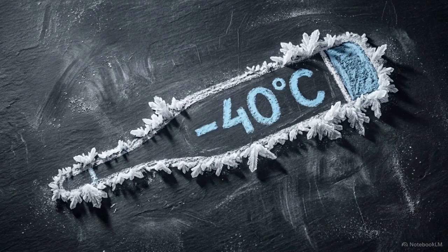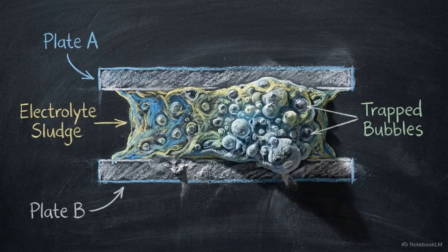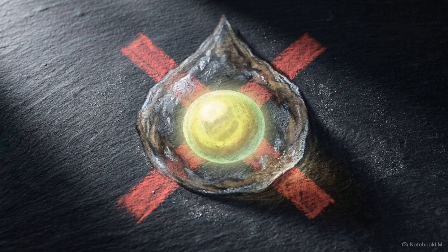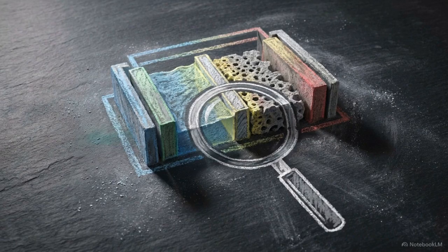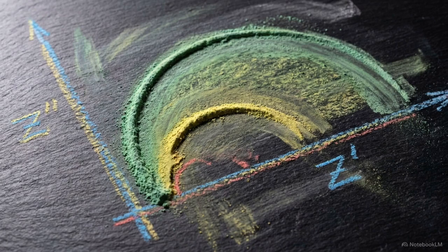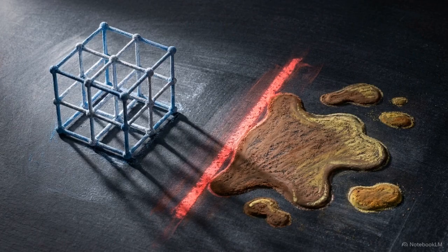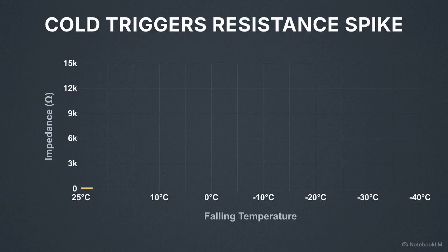As ambient temperatures drop toward -40, the liquid electrolyte inside the battery thickens, viscosity spikes, and bulk ionic conductivity plummets. It's logical to assume this thick liquid is the primary reason the battery stops working, but the data reveals a different bottleneck. Electrochemical impedance spectroscopy reveals that the cell's resistance is concentrated at the boundary between the liquid electrolyte and the solid electrode. This Arrhenius plot tracks different impedance factors as temperatures fall.